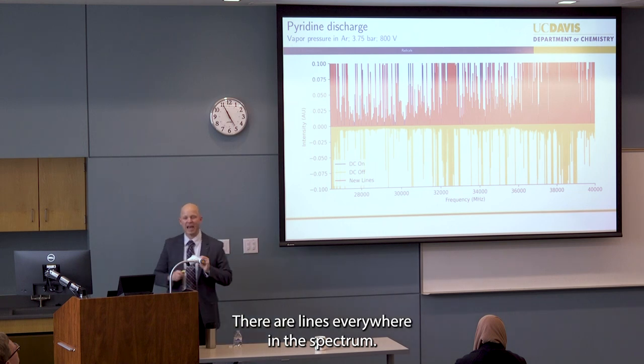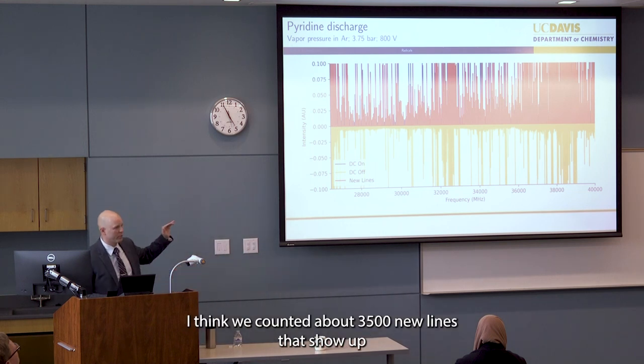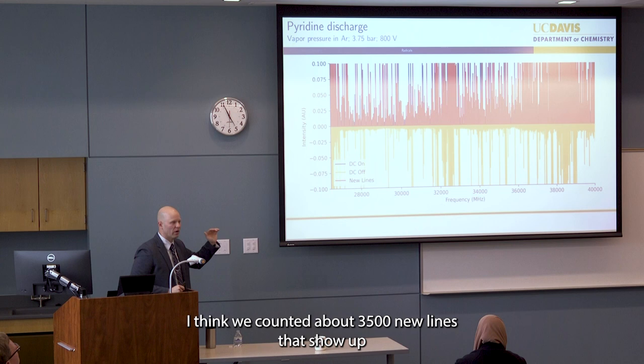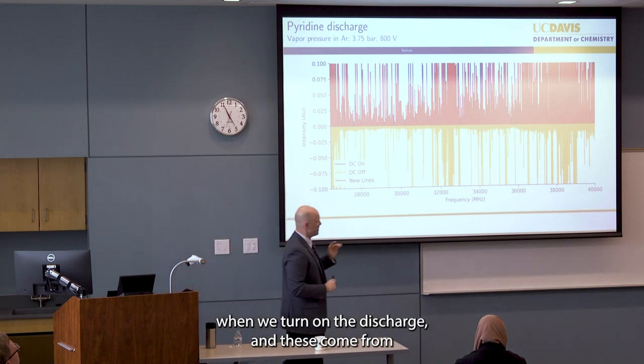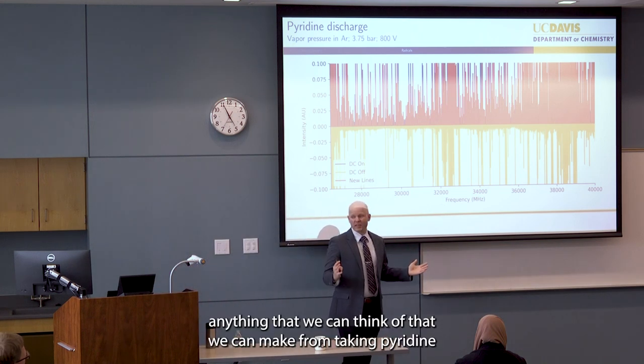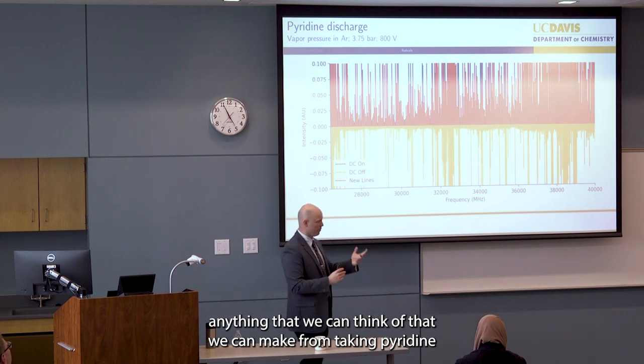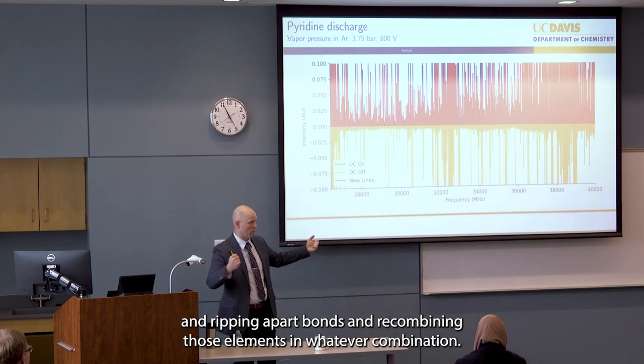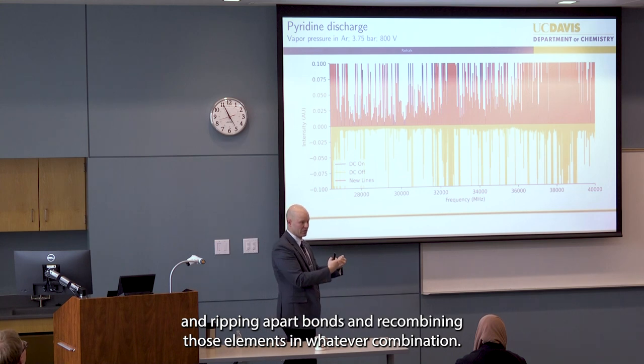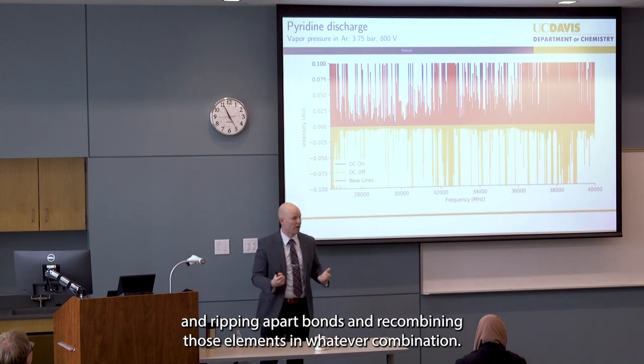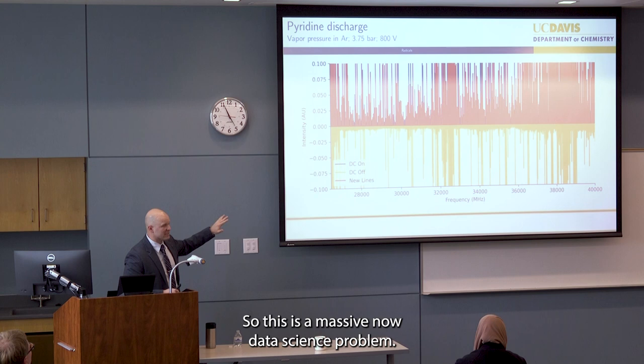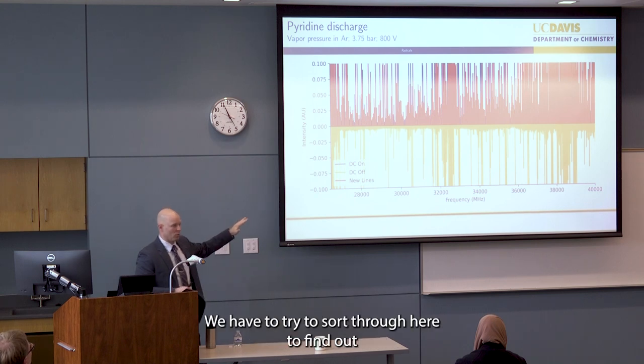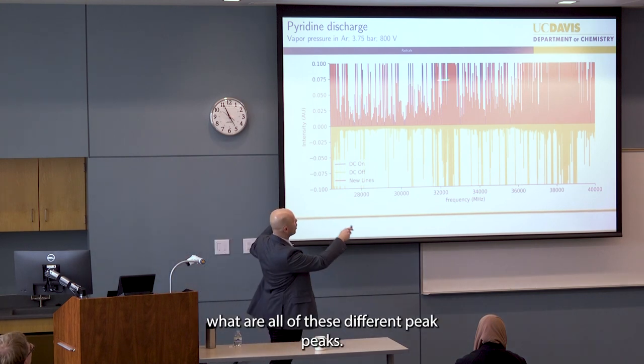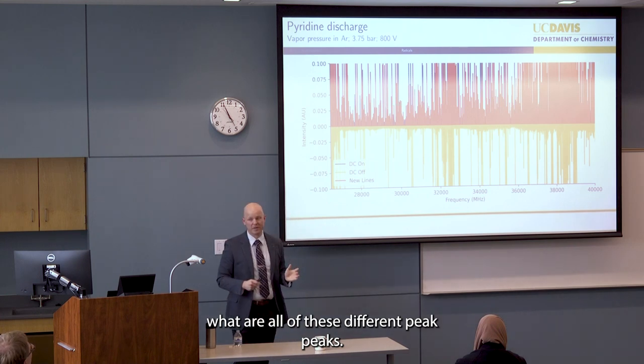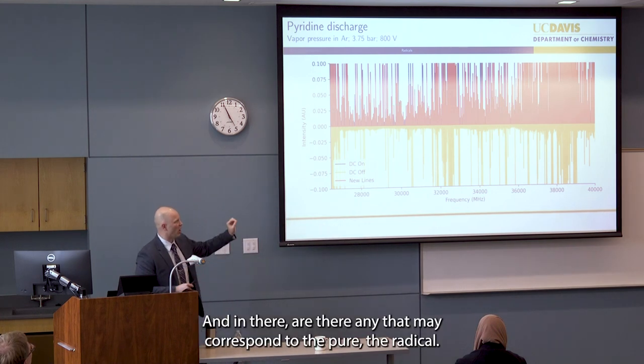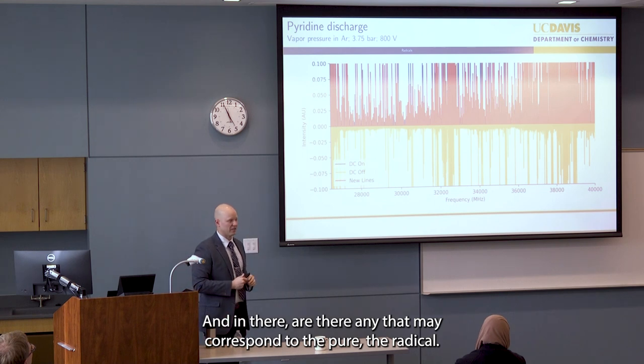There are lines everywhere in this spectrum. I think we counted about 3,500 new lines that show up when we turn on the discharge. And these come from anything that we can think of that we can make from taking pyridine and ripping apart bonds and recombining those elements in whatever combination. So this is now a massive data science problem. We have to try to sort through here and find out what are all of these different peaks. And in there, are there any that may correspond to the pyridyl radical?